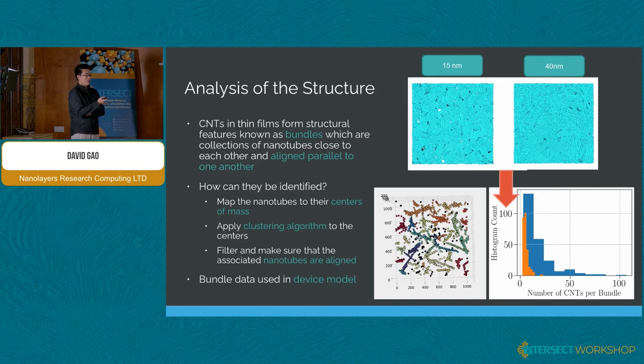Okay, so we have this massive library of films, with different lengths and distributions of nanotubes, and we can account for how you deposit them. Then suddenly you hit the problem where you're trying to discuss with the experimentalists, and you don't actually know how to tell them whether or not your films are good, because amorphous structures are hard enough to describe to begin with. You can try to use things like the radial distribution function, bond length and angle distributions, and some rough coordination numbers, but when all your particles are huge tubes, most of those concepts don't quite work. So we've tried to develop new ways of describing these films so that we can analyze the experimental results, essentially a new language in which we can describe the film structures to them.